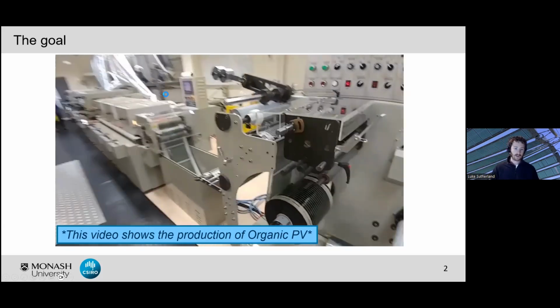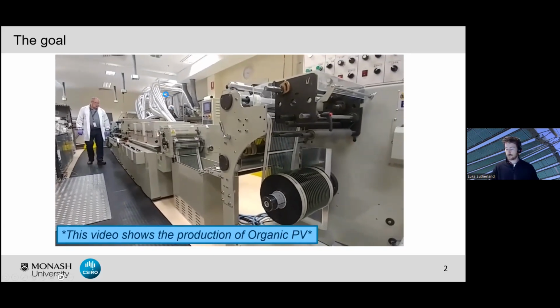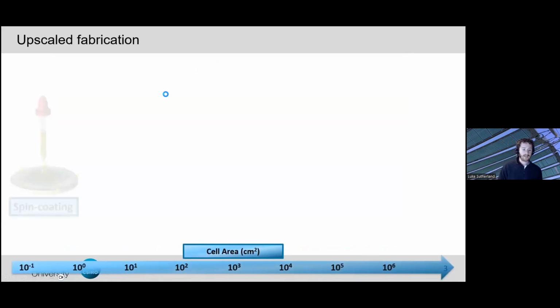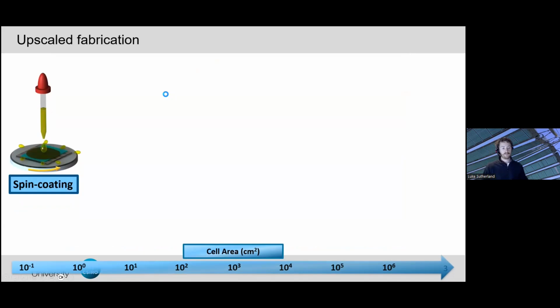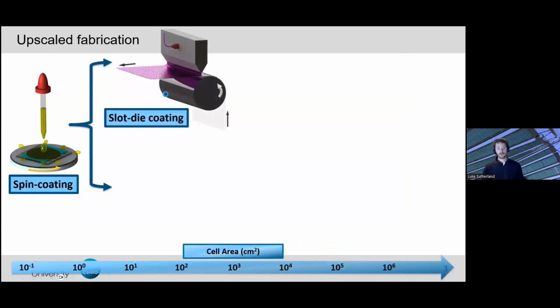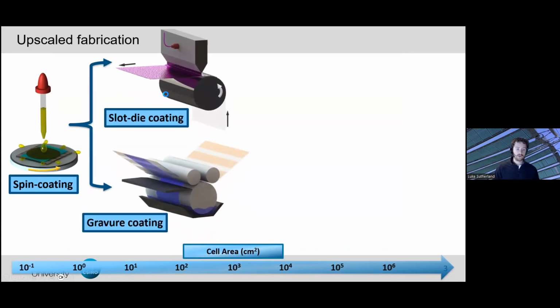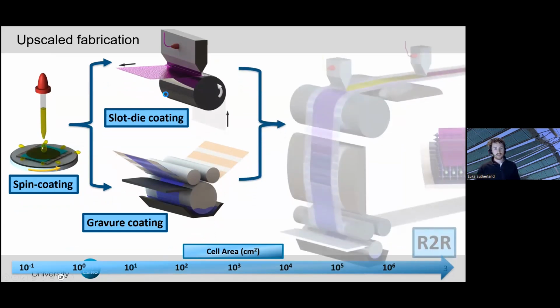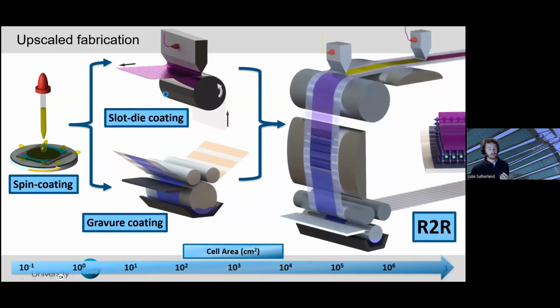However, this is our current goal for perovskite solar cells. And I'll tell you what, we're not too far off. But really what we're talking about here is transitioning away from our typical means of device fabrication, which is often done via spin coating in our highly controlled inert environments, and progressing towards readily scalable printing and coating techniques, such as slot die coating or gravure coating. Now, the benefit of these is that we can seamlessly integrate these into our roll-to-roll fabrication process, where, as we saw before, we can sequentially deposit each of our functional layers to go from small area cells from the research scale all the way through to larger area modules, interconnected modules, and then progress towards commercial scale products in the end.